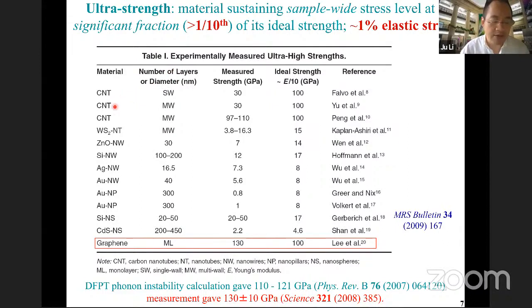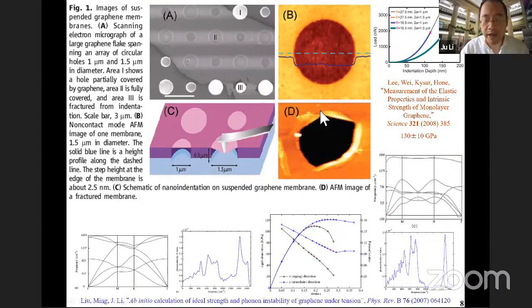And this applies to materials like carbon nanotubes, zinc oxide nanowires, nanoparticles, nanospheres, and graphene. This column is the experimentally measured tensile strengths. And we can see that you can get 30, 50%, and sometimes even exceed the theoretically computed ideal strengths a little bit. As an extreme example of this, consider two-dimensional graphene. In 2007, from density functional theory calculation, we predicted a strength of about 110 to 120 gigapascal in tension. And then a year later, there was an experiment that gave 130 gigapascal.